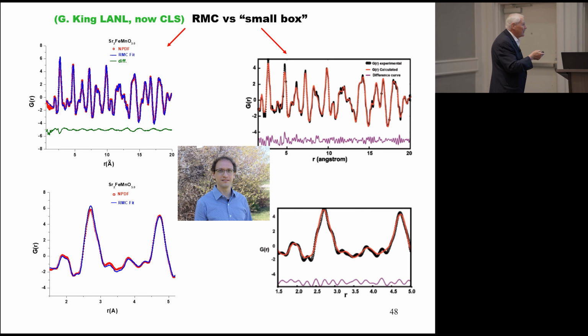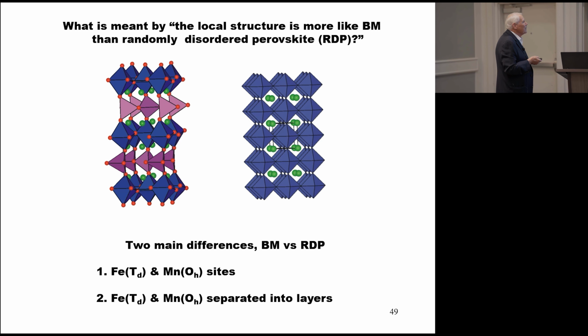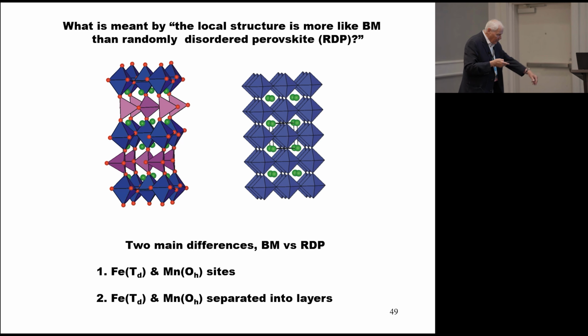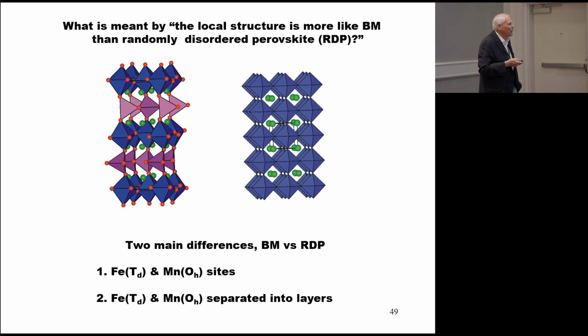And so we carried out RMC modeling, and of course you do a whole lot better, as you might know, with RMC. That is, if you compare that thing with that one, it's a much better fit. And if we look at the near neighbor, the very close neighbor bonding portion, you see quite a nice fit with the RMC approach, and a much poorer one with the small box.